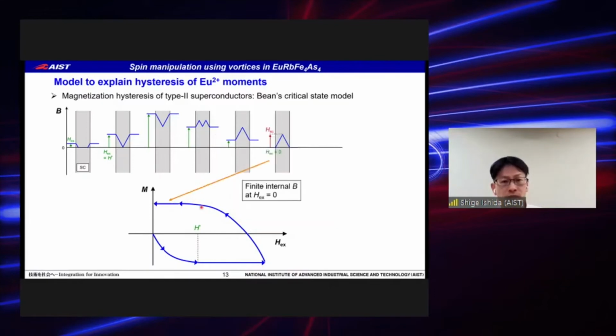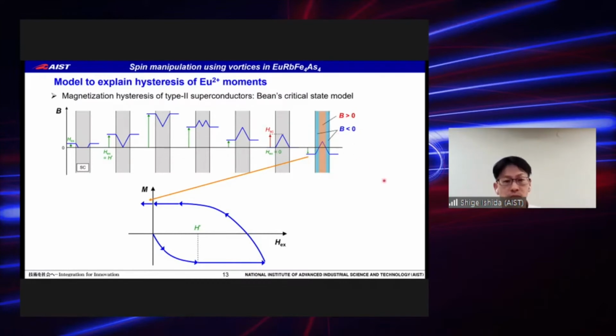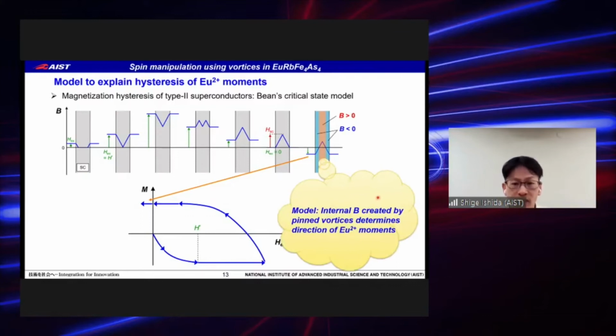Then at zero field, there is a finite field inside the sample, with strength depending on the vortex pinning ability, or Jc, of the material. Moreover, at the slightly negative field region, B becomes negative or positive depending on sample position. Here we assume that the internal B created by the pinned vortices determines the direction of the europium moment, and we model it accordingly.